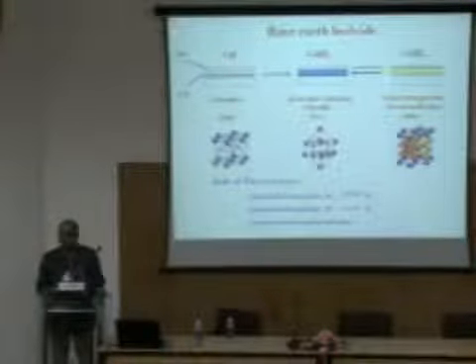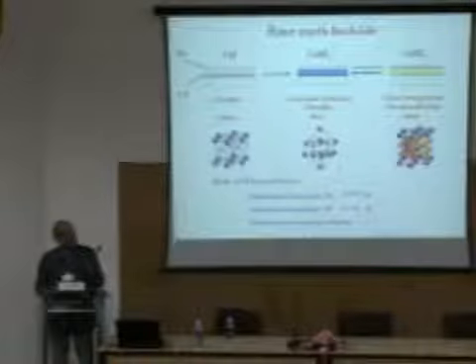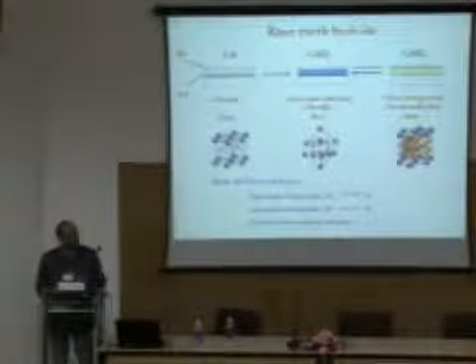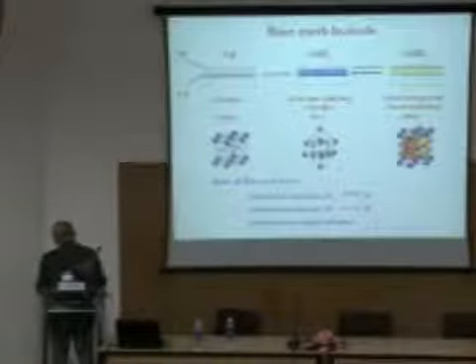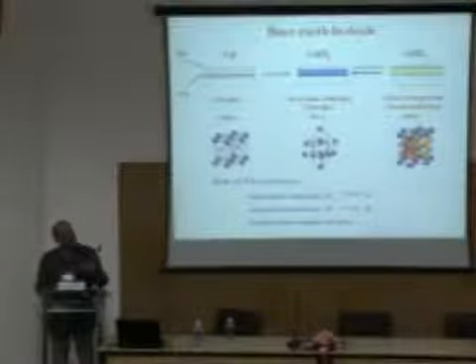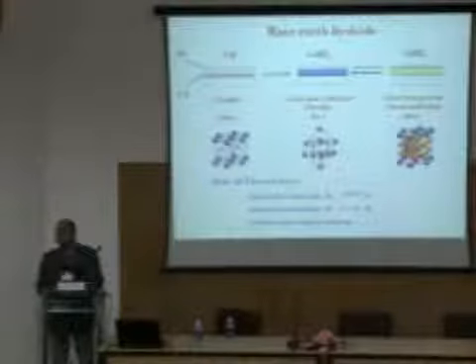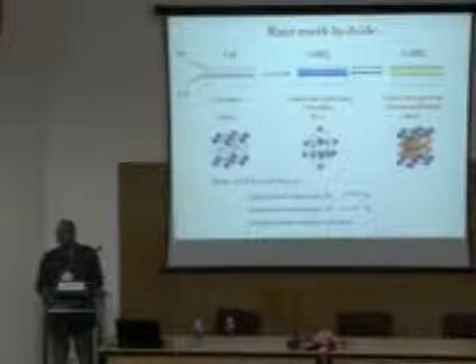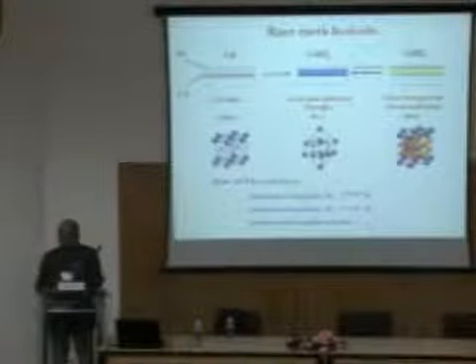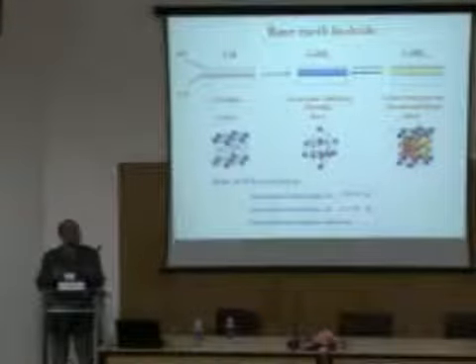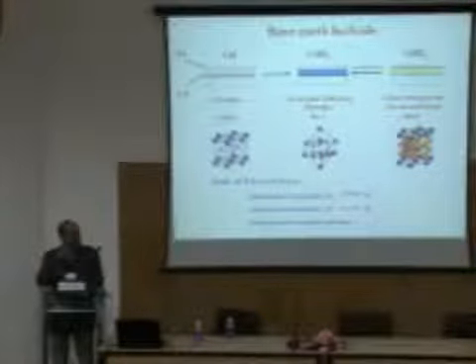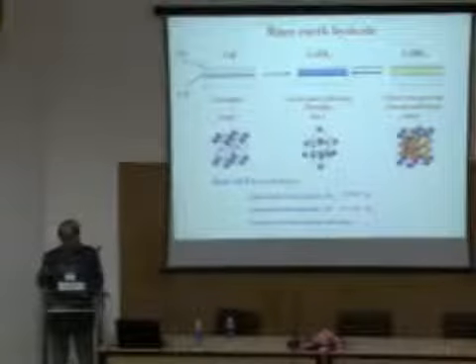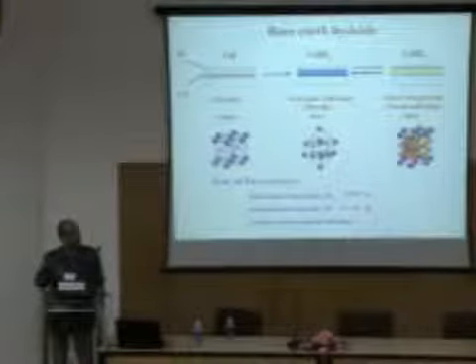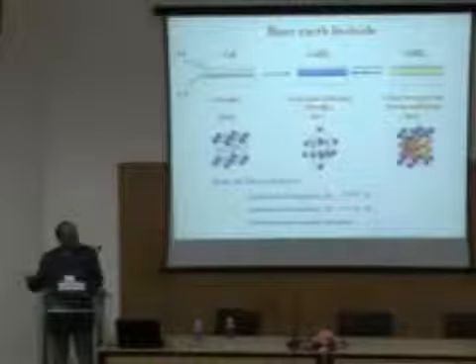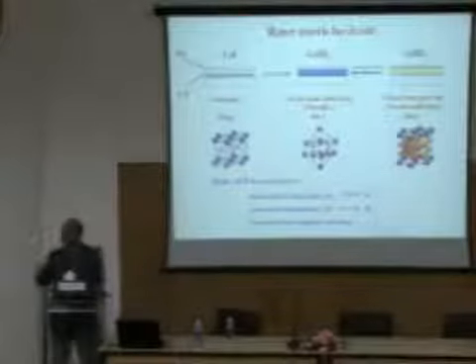This effect was first reported something like 6 to 7 years back, and a lot of theoretical and experimental investigations are going on to understand how the metal to insulator transformation and the crystal structure transformations are taking place. Another very interesting and complicated issue is that these 2 transformations are not related to each other. The metal to insulator transformation has nothing to do with the crystal structure transformation, because there are rare earth materials like praseodymium I mentioned.